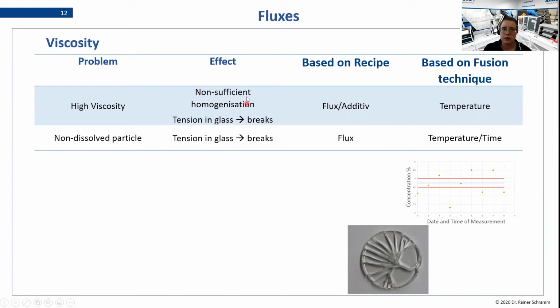What happens when there's insufficient homogenization, but the glass doesn't break? Then you will get something like this here. You have a graph that is showing concentration and the date and time of measurement of different samples that were done. And you can see that I'm having a sky full of stars there, and I actually want the measurements to be somewhere between these red bars. So it will just have very poor precision there.